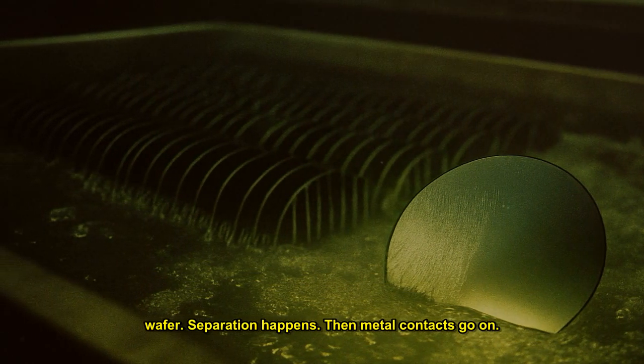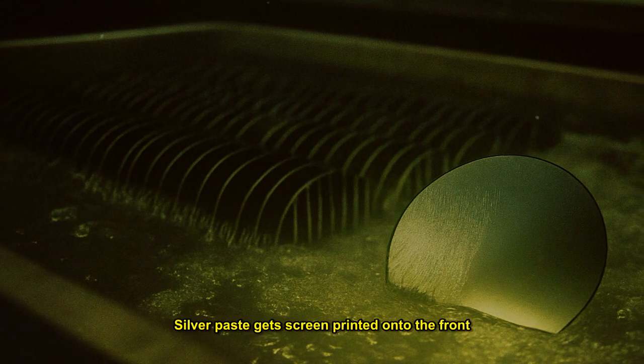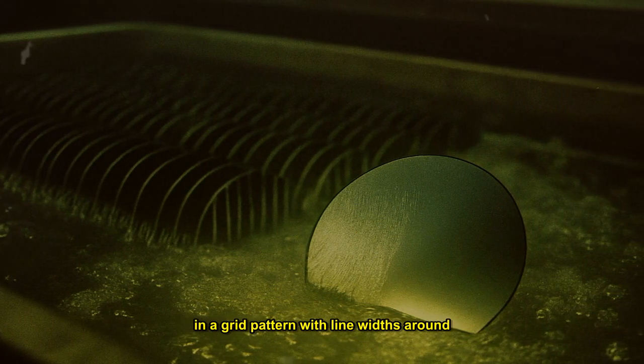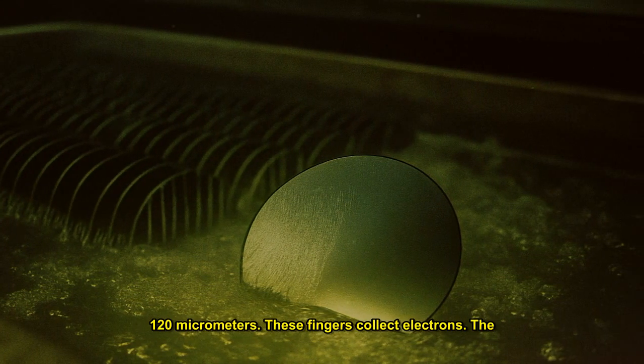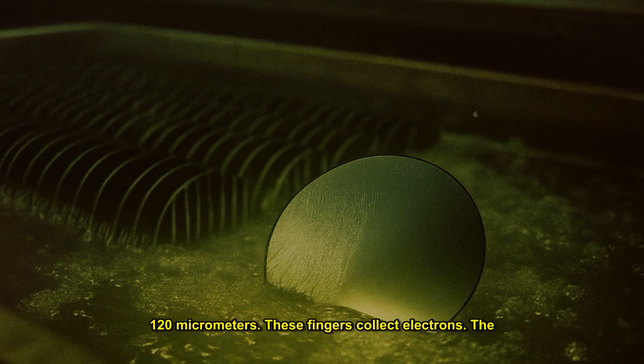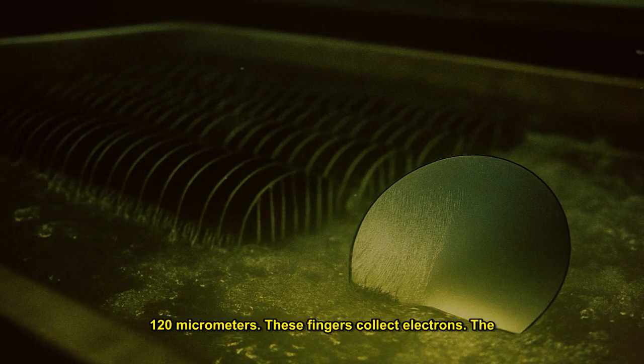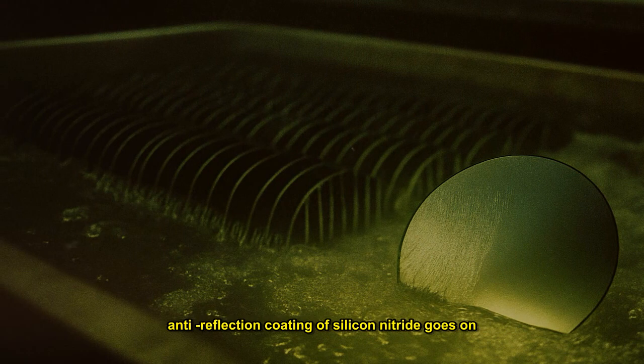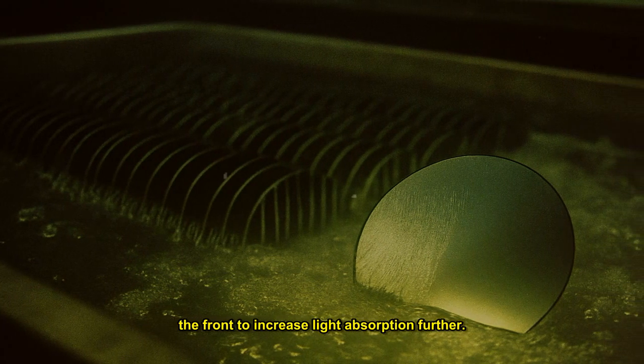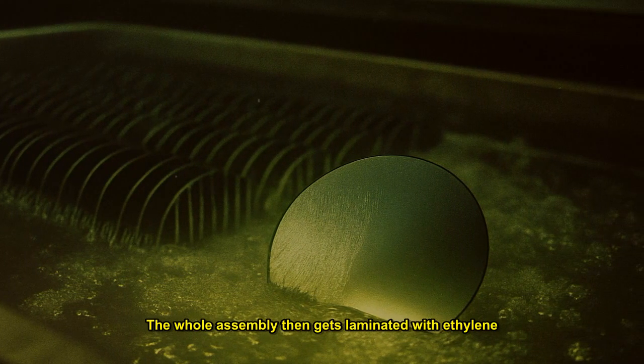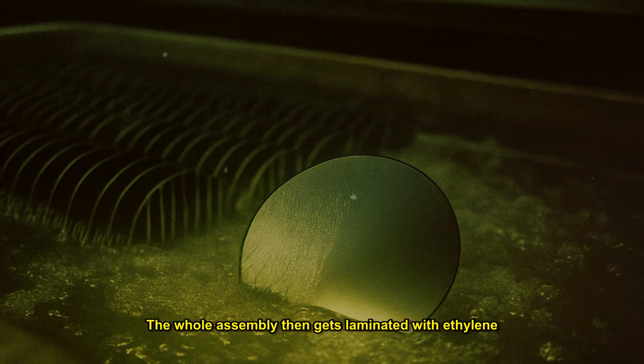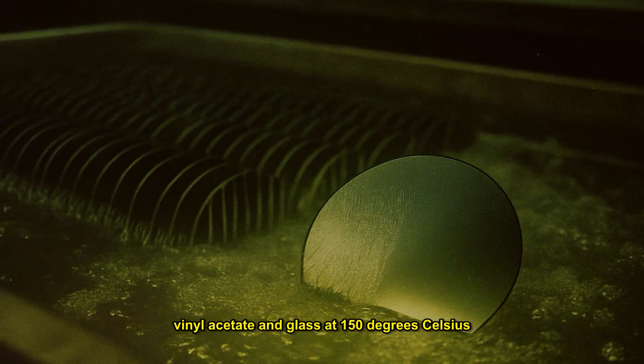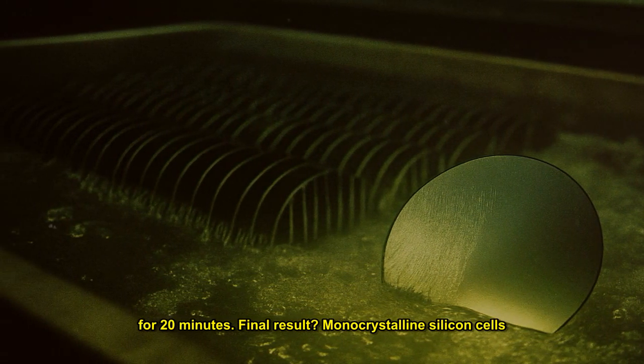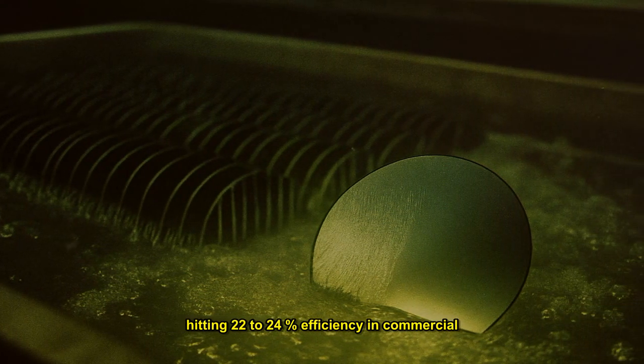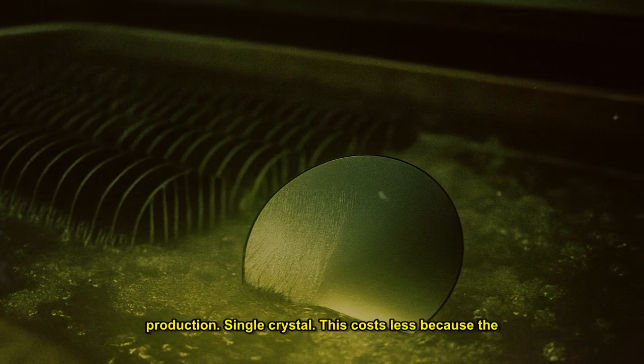Separation happens. Then metal contacts go on. Silver paste gets screen printed onto the front in a grid pattern with line widths around 120 micrometers. These fingers collect electrons. The back gets a full aluminum layer to collect holes. An anti-reflection coating of silicon nitride goes on the front to increase light absorption further. The whole assembly then gets laminated with ethylene vinyl acetate and glass at 150 degrees Celsius for 20 minutes. Final result? Monocrystalline silicon cells hitting 22 to 24% efficiency in commercial production.